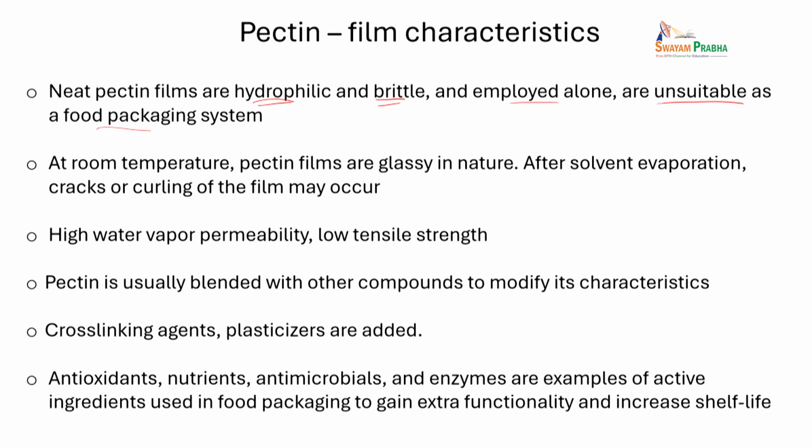So that is one issue with native pectin. Especially when the solvent evaporates, you will see cracks and curling. The film becomes a little unstable, and it has very high water permeability and very low strength. These are all problems with native pectin.